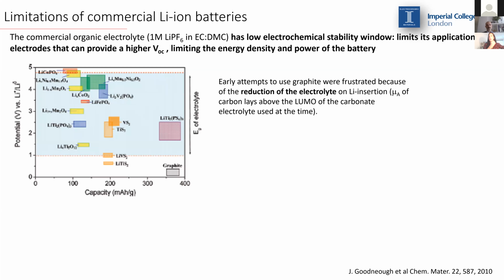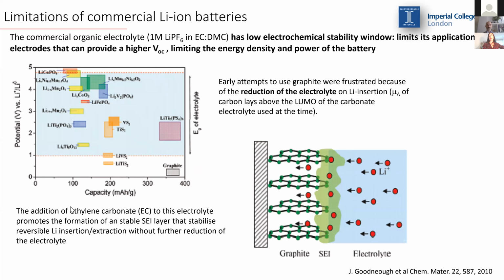The liquid organic electrolyte that we are commercially using nowadays has an electrochemical stability window that is poor at low voltages. In fact, it's not stable in contact with graphite, which is the commercial anode that we are using nowadays. That initially prevented the commercialization of secondary batteries, and then it was discovered that by the addition of additives such as ethylene carbonate, we can stabilize an SEI layer that is thin but also an electronic insulator, so it doesn't allow the continuous reduction of the electrolyte, but is permeable to lithium movement, and therefore allows for the reversibility and cyclability of the batteries.